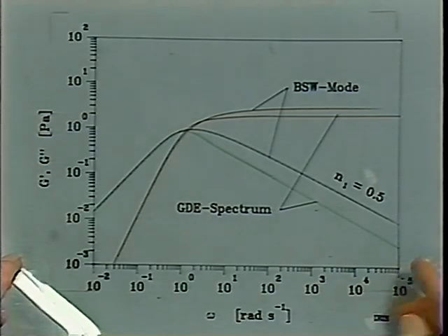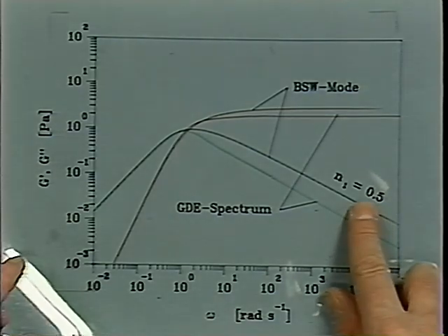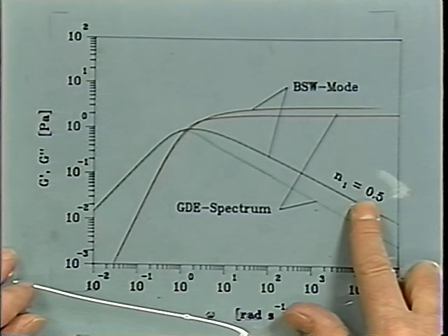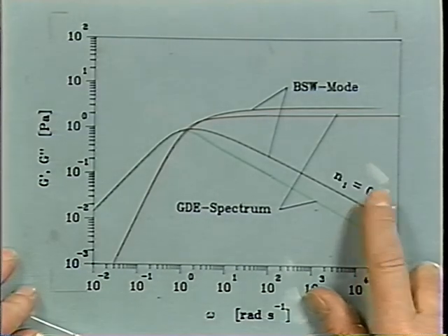So that's a big difference. We find a slope of about a quarter, 0.25 or 0.2 for most materials, and here 0.5 is somewhat too steep. So the Doi-Edwards model probably gives the lower bound of that spectrum. It just says that molecules are not able to cross. That's a hindrance. But something else has to enter in the model, some other dissipation mechanisms which then increase the value of G prime, G double prime in the entanglement region. And the question is, what is that? What additional physics has to be entered in that?